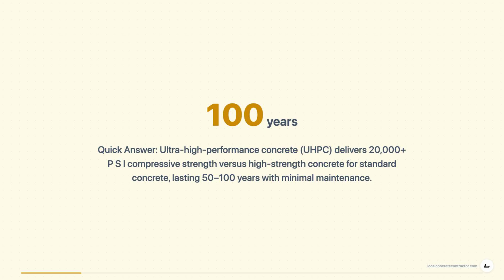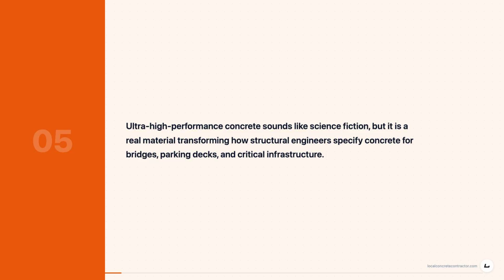20,000-plus PSI compressive strength versus high-strength concrete for standard concrete, lasting 50 to 100 years with minimal maintenance. It costs $3,000 to $5,000 per cubic yard, roughly 10 times standard concrete, but eliminates rebar corrosion, freeze-thaw damage, and spalling in harsh environments. Ultra-high-performance concrete sounds like science fiction, but it is a real material transforming how structural engineers specify concrete for bridges, parking decks, and critical infrastructure.